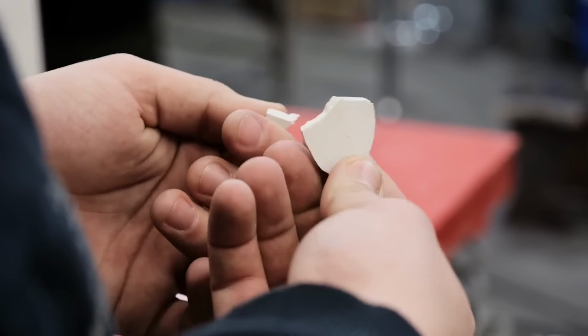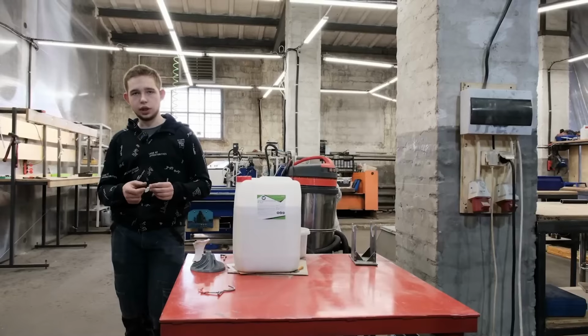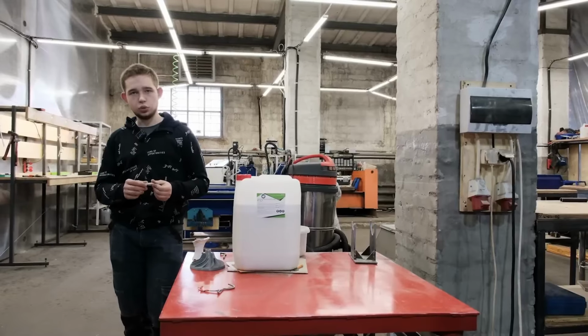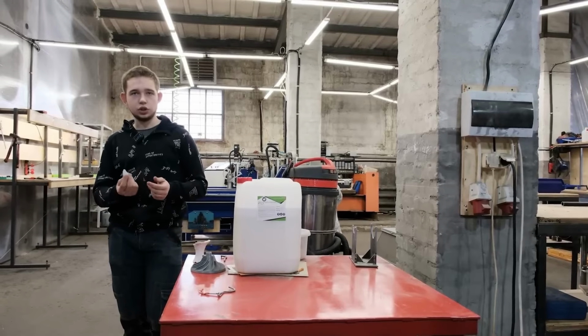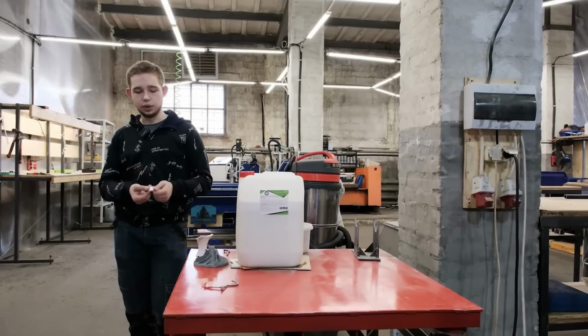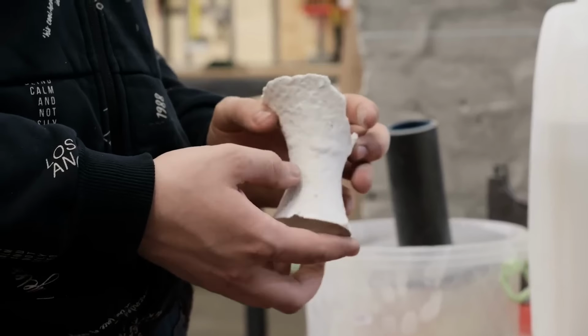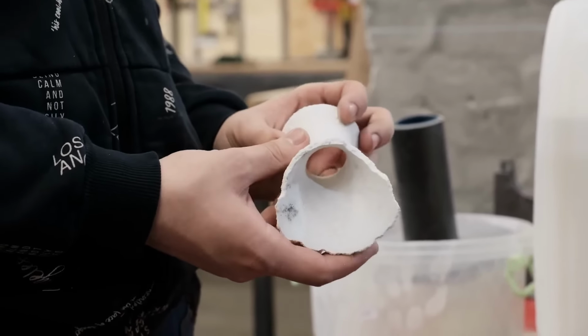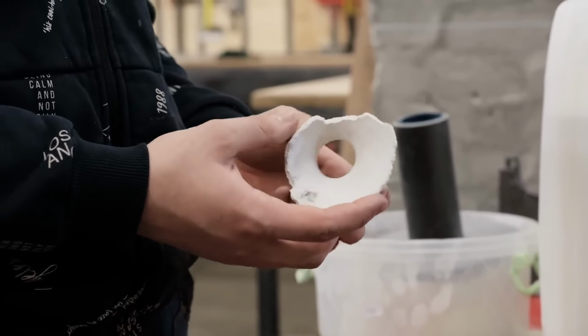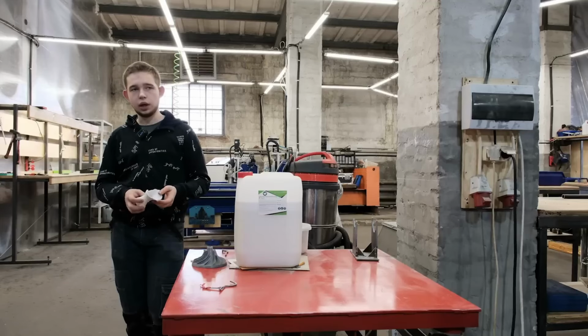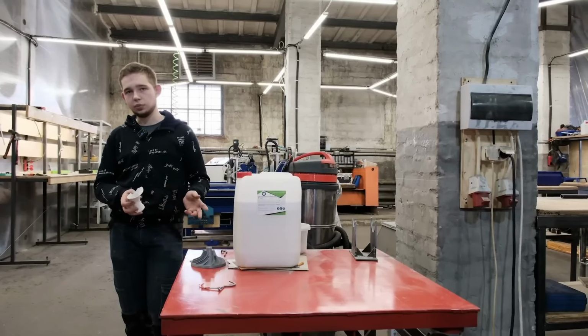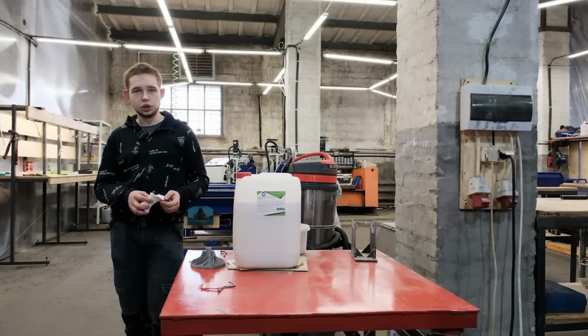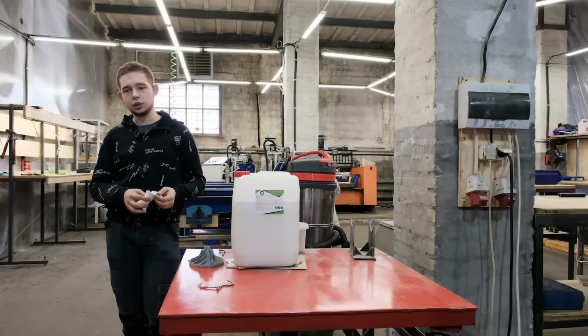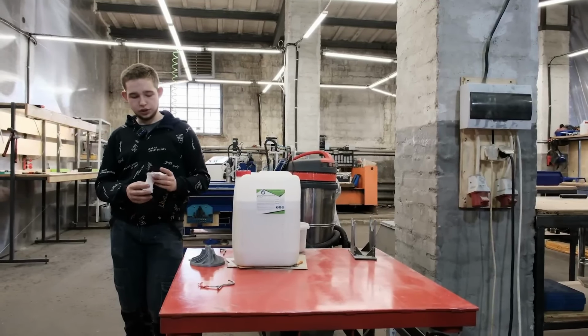In this particular case, electrocorundum was specifically utilized. F1200 filler results, essentially, in aluminosilicate ceramics. With a coarse fraction filler, you also obtain this type of ceramic shell. To form a shell suitable for casting, it is necessary to apply approximately 4 to 8 layers, with intermediate drying periods between each layer, continuing until the shell is completely dry and the binder has fully set.